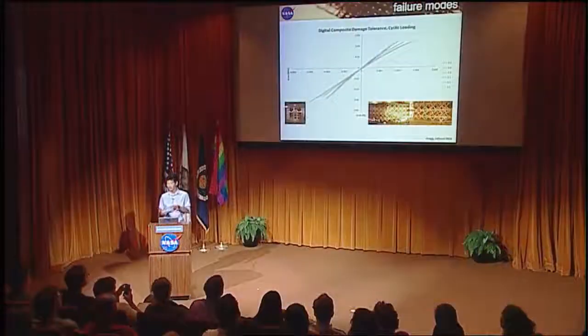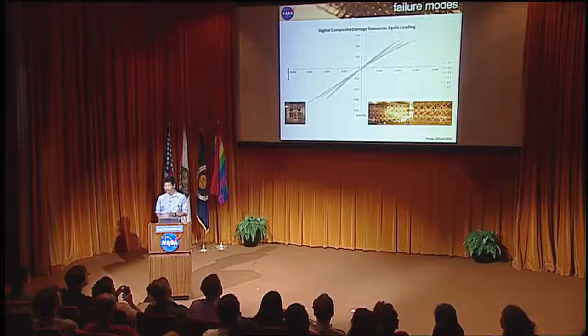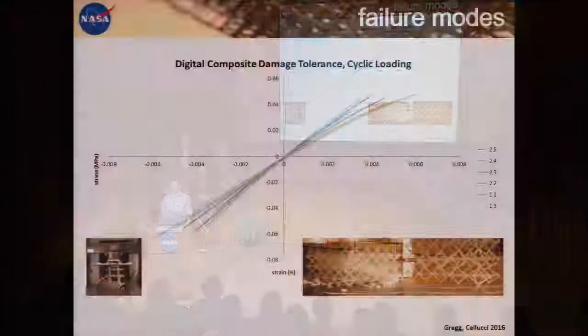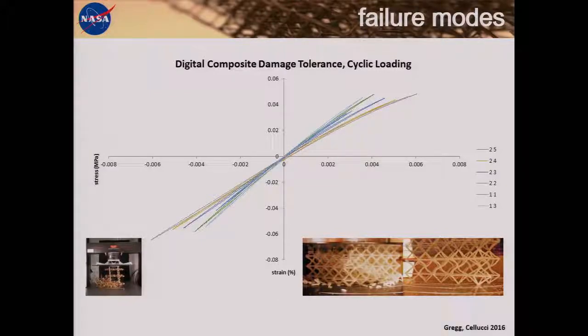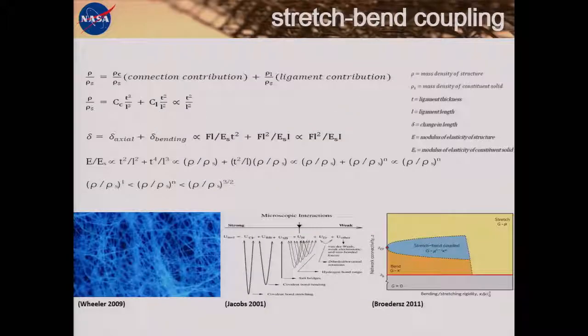A significant perceived pain point with fiber composites is with failure modes of typical engineered parts. A caricature of the stress-strain curve for a typical fiber composite part is a straight linear elastic line that abruptly ends in breakage. And what this means in a practical sense is that breakages can be accompanied by elastic unloading of a great deal of stored energy. And this can be quite dangerous. So now we still have a great deal of work to do on this topic of failure mechanisms for digital composites. But early tests suggest the possibility of being able to tune materials to behave in new ways. So this is an open frontier in material science.